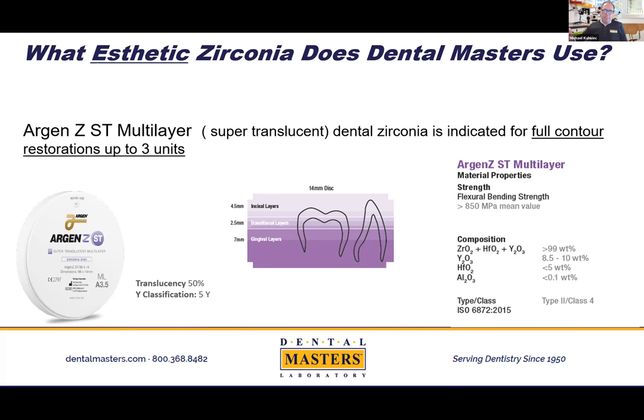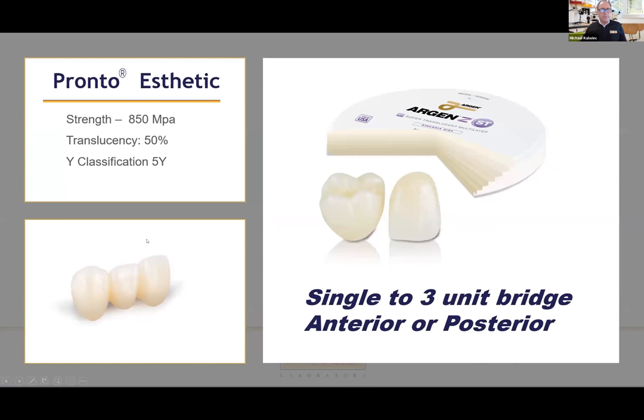We see a much better blending from gingival to incisal with this material right out of the sintering oven. It has a 50% translucency, and it is classified as a 5Y. 850 megapascals, literally double the strength of Emax. I liken it to Emax on steroids. So Pronto Aesthetic, again, the Argen super translucent multi-layer, 850 megapascals, 50% translucency.